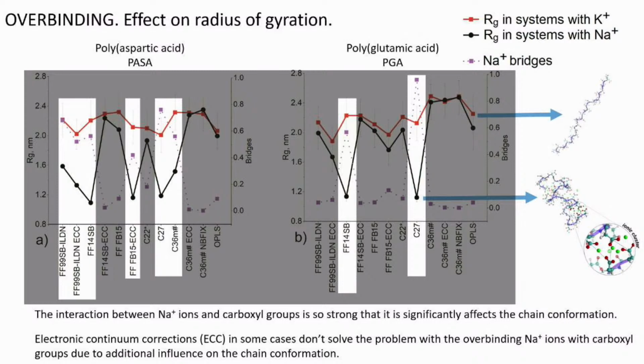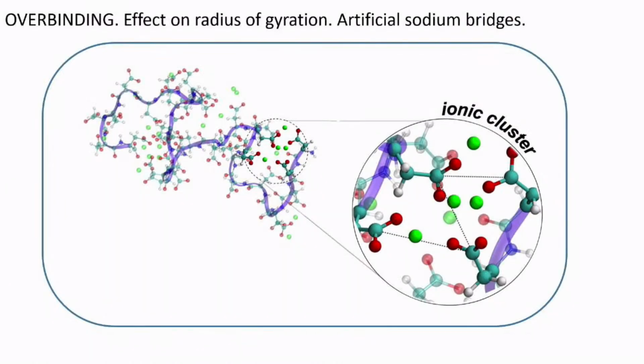Interestingly, electronic continuum corrections in some cases don't solve this problem, and we think that it is due to the fact that by decreasing the charge on carboxyl groups, we also decrease the repulsion between them, and it artificially changes the value of radius of gyration of the chain, and effectively increases the density of the charge of the chain as a whole, and this leads to additional adsorption of sodium. So this is an example of an ion bridge, a classical example of some artificial results, and as you can see, this bridge can consist of several different carboxyl groups and several ions.